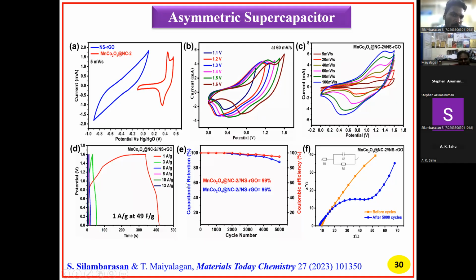So the applied potential is around minus 0.12 to 0.55 for the positive electrode, and minus 0.12 to minus 0.9 for the negative electrode. Then figure B is the same standard but with different potentials measured from CV, like 1.1 volt and 1.6 volt. And next, figure C is the cyclic voltammetry at scan rates from 5 to 100 millivolt per second. The applied potential is 1 to 1.6 volt.